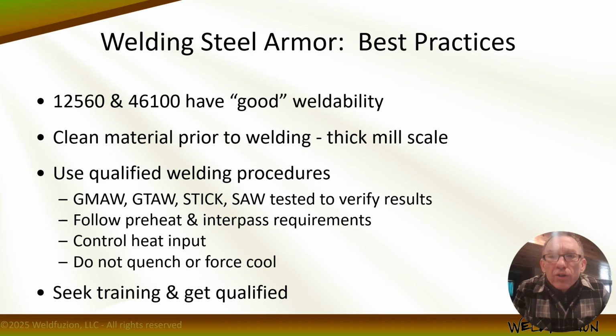Right? So with too little heat input, we risk fusion and cracking issues because we may not have the dilution that we need, especially on aluminum alloys. And with too much heat input, we can soften the material, reduce strength, and thereby reduce protection of the armor material. If you haven't welded these materials before, it's recommended that you seek training and get qualified. Only qualified personnel are allowed to weld armor according to all codes and standards.